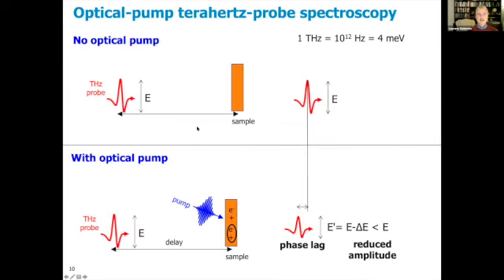And to investigate that, we used, first of all, the technique of optical pump and terahertz probe spectroscopy. Now, what's that? If you have a sample here, let's say a cuvette with these nanosheets, we produce a terahertz probe pulse that is like a single cycle of an oscillating electric field. The time duration of this cycle is about a picosecond. So we get 10 to the 12th hertz or terahertz frequencies in there. And that is a photon energy of about 4 millielectron volt. Now, if we don't photo-excite the sample, the terahertz just goes through the sample. But if we optically pump the cadmium selenide nanosheets, then we either produce free charges, excitons, or both.